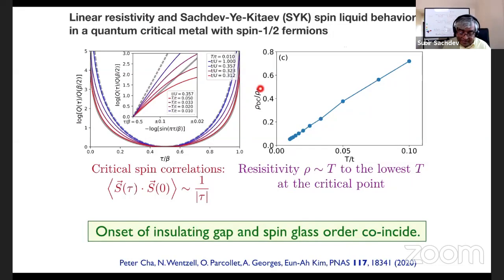And they computed the DC resistivity, and this is to answer your question, Andre. They found linear in temperature resistivity down to 0.01 of the bandwidth. So this is really extremely low temperatures. There have been a lot of earlier works with some indications of linear resistivity from various DMFT-like methods, but those are generally at much higher temperatures. This is down to extremely low temperatures. You see linear resistivity only at this critical point, with a negligible residual resistivity. So at least here, there's some numerical evidence of very small residual resistivity, and mostly linear. But this regime is very much out of analytical control, at least by the methods I've talked about so far. Okay, so that's this critical point.